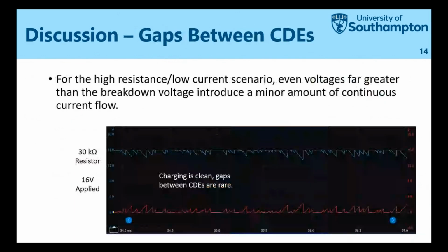So the clincher I'm currently fighting with is trying to explain why there are gaps between some discharge events, especially in the high resistance scenario. This case is the 30 kilo ohm resistor. That's a really low current, and I've been able to apply 16 volts. That's really high, far beyond what the breakdown voltage was.